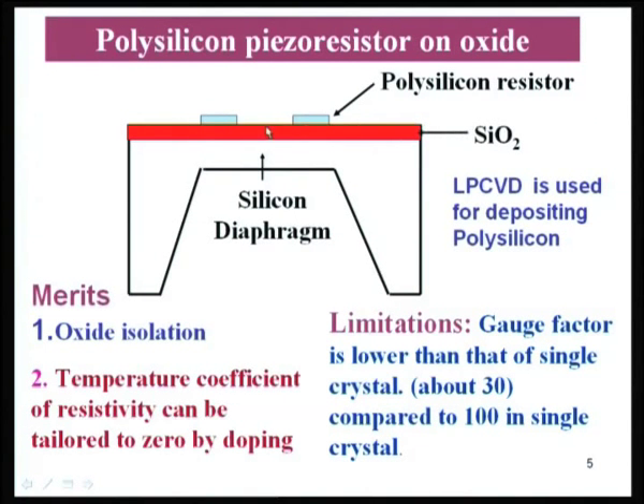Okay. Now, this polysilicon is deposited by a technique known as low pressure chemical vapor deposition. What is done is, into a heated furnace you pass silane, SiH4 gas, it will decompose into silicon and hydrogen, and the silicon will be deposited on this oxide that will turn out to be polycrystalline. This deposition is done at about 620 degrees centigrade. Okay. So, you need 4 resistors, what you do is deposit polysilicon everywhere, pattern them, dope them, you get the resistors. We will go through those steps now.